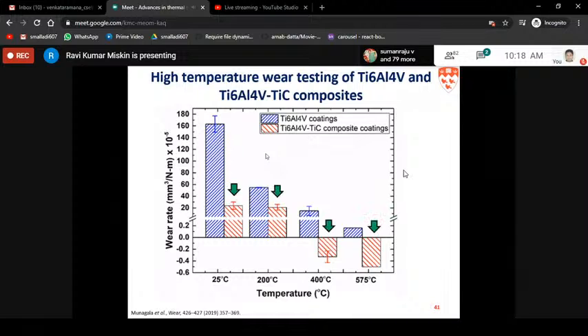Those green arrow marks are basically our composite coatings, and the blue ones are the metal coating. So when you have a composite coating, it wears less. And secondly, if you see at 400 and 575, the counterface wore basically. The coating was highly protective, which means that at higher temperatures, our wear resistance is pretty much improving. And also, when compared to pure Ti64, at all temperatures, the composite coating is performing better.